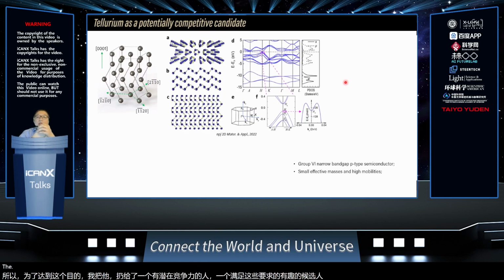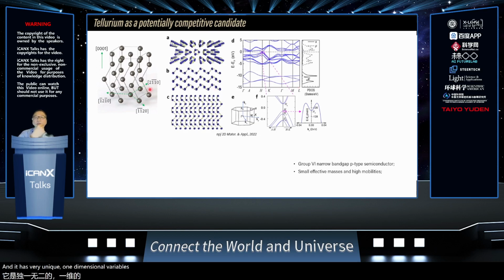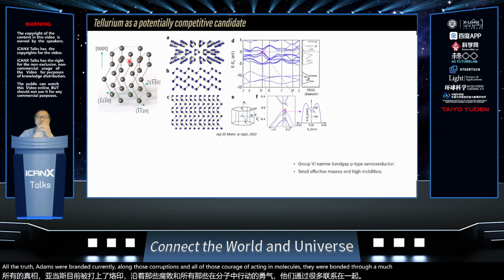So Tellurene is a group 6 narrow band gap p-type semiconductor, and it has a very unique one-dimensional van der Waals crystal structure. So in the crystal structure of tellurium, all the tellurium atoms are bonded covalently along those chiral chains. And all of those chiral chains, like DNA molecules, are bonded through a much weaker interaction.